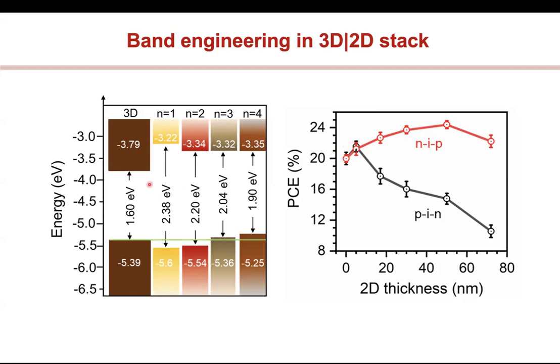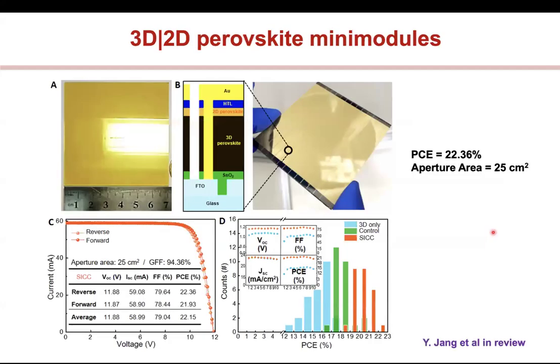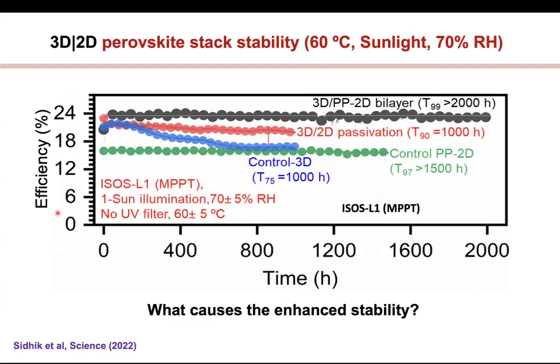Whereas if I make a PIN device where I try to move an electron, I get some passivation effect in the beginning, which is what I showed you earlier, but then I get this precipitous drop in my power conversion efficiency. Okay. So this is good. And then of course you can scale this method up. Now we have made some modules which are about 25 centimeters square, and this is a scalable method, which is kind of in review. Okay. Now, when we looked at the stability of these type of devices, you see that this is a stack of the 3D and 2D, and you can see that now it gives you stability, which is over 2000 hours without any degradation.